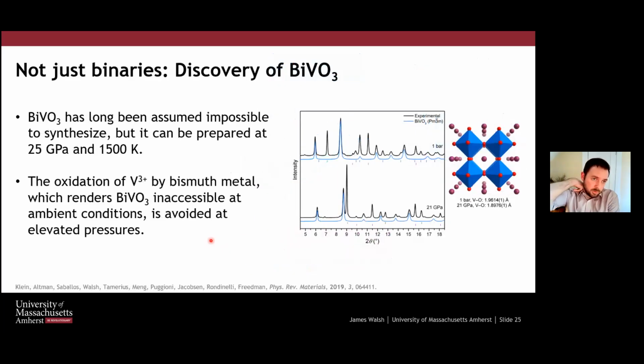Okay, and it's not just binaries, so I don't want you to think that all we do is 2 elements with bismuth. We sometimes do 3 elements with bismuth, and this is an example of the discovery of bismuth vanadium perovskite. This is something that had been published on in the past in the context of why isn't bismuth vanadate perovskite synthesizable, and it's because you have a redox reaction where the vanadium 3+ is oxidized by bismuth. This is avoided at high pressure, and it turns out that you can actually synthesize and recover bismuth vanadium perovskite.